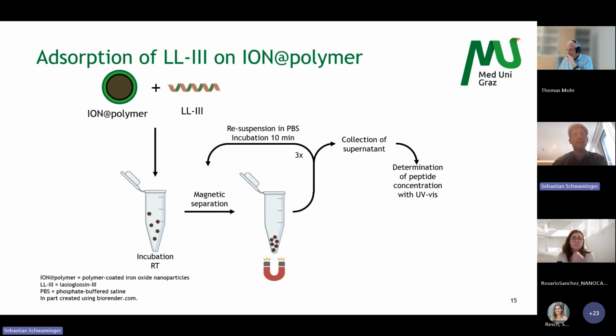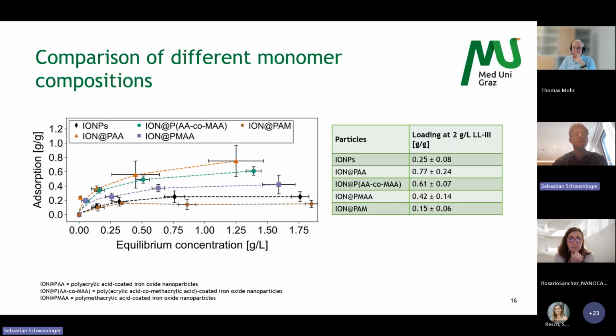In our case, we then do an adsorption of the peptide to the polymer coated nanoparticles. The easy thing for all our assays is that we can use magnetic separation to test and verify them. We saw that it's quite easy to get a high load of the peptides to the nanoparticles, and it's not only a high load which is specifically bound, but it's also not easily released, and therefore is the first part of having an effective drug delivery system with a high load of a drug.